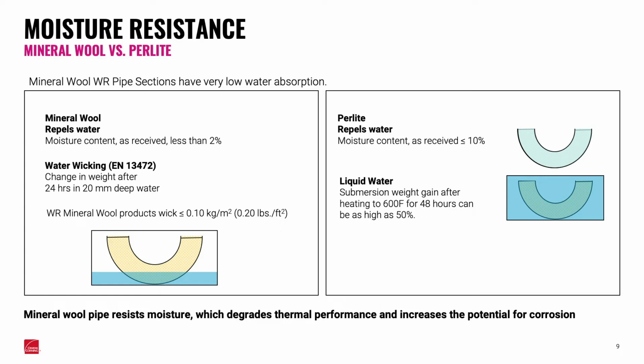Now, looking at perlite on the right-hand side of the slide, again, the moisture content as delivered can be up to 10%. There's also the submersion test that we talked about, and this is a requirement for the standard specification for perlite, which is ASTM C610, and that allows up to a 50% weight gain after the product's been conditioned at a higher temperature for up to 48 hours.